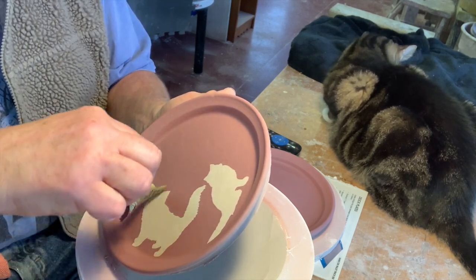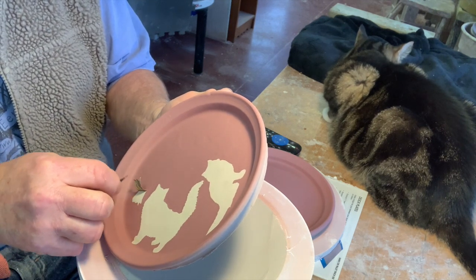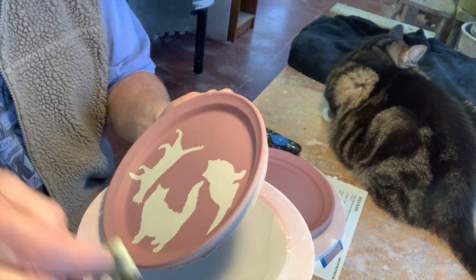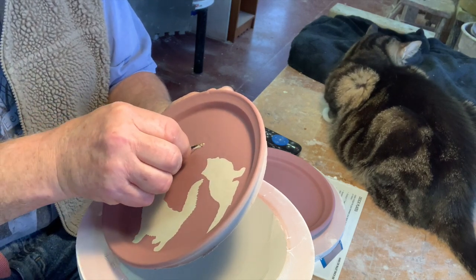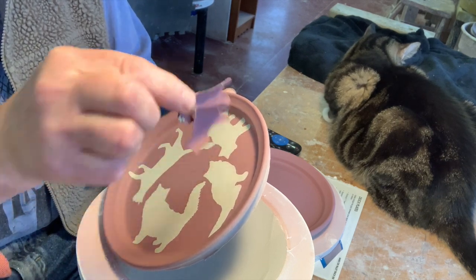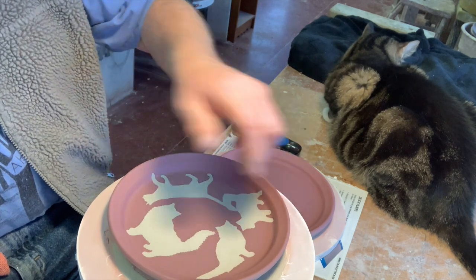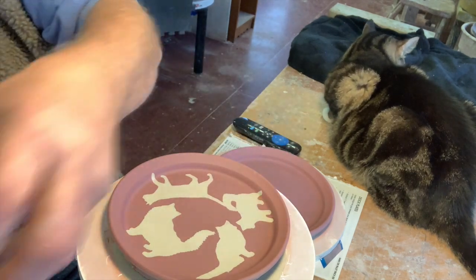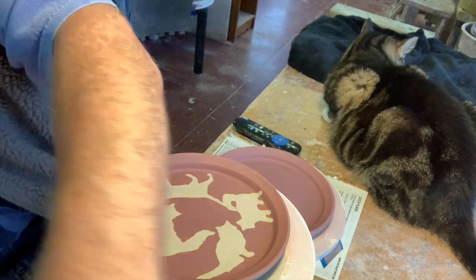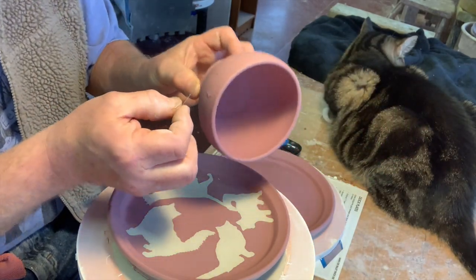So this is the more perfect time to remove a paper stencil. When it's super wet, the risk is just that it tears and drops back down. But at this stage, when the clay isn't dry, it's not even quite leather hard yet, but it's touch dry and you can take the stencils off very easily. And then the same with the balls. Oh, this is a rabbit one. Do I have a cat one here? Yeah. So the balls,